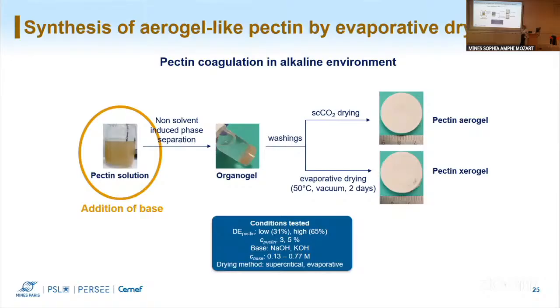It is interesting because when we add high amount of either sodium hydroxide or potassium hydroxide, we have a coagulation. We don't know exactly what is happening, but we suppose that it's a coagulation due to the ionic strength of our solution. And both for sodium and potassium, we have coagulation for the same amount of base. But then the structure of the network is very different. So first we have a coagulation of the structure because of the ionic strength. And at the second step, we have a different mechanism of chain association that's very much dependent on the metal ion. This is what we suppose. So we see that the ionic strength is the same, they have the same effect, but then we need to understand the metal ion exactly what is the mechanism.